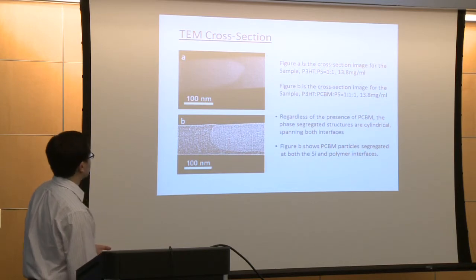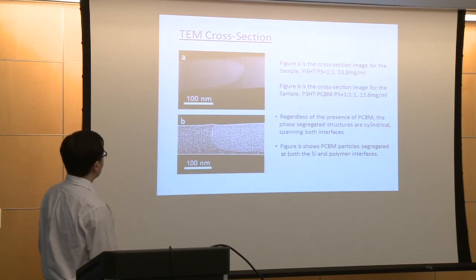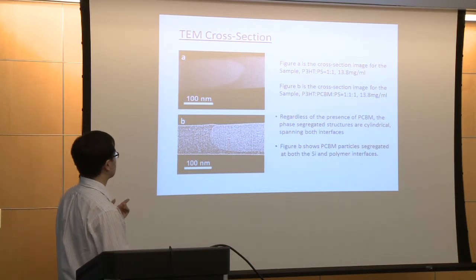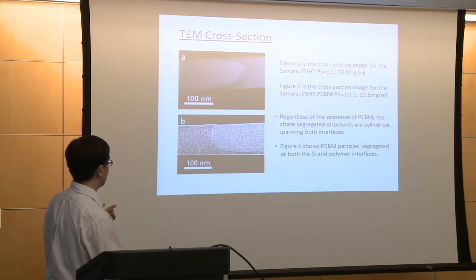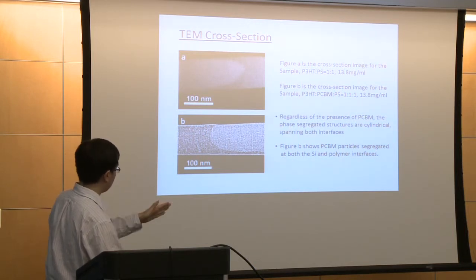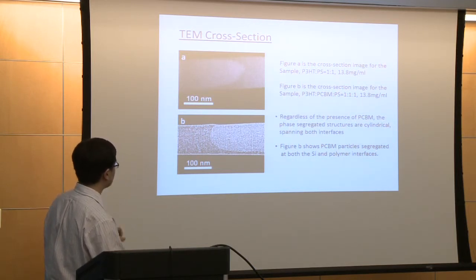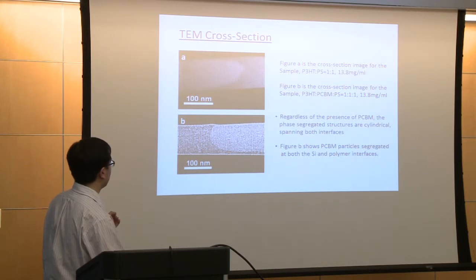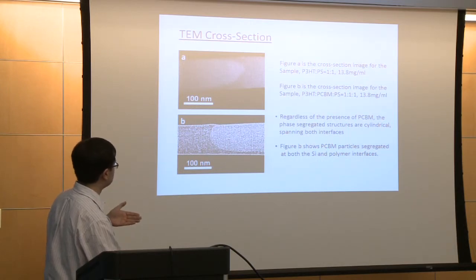So this is our result from the TEM cross-section. The top one is the sample without PCBM, and the bottom one is the sample with PCBM. We just picked one side of the domains, but the other side is actually the same as this one. So we find that regardless of the PCBM presence, there's always a column structure formed at the cross section.